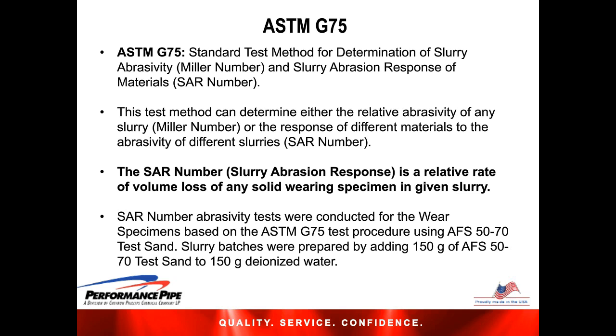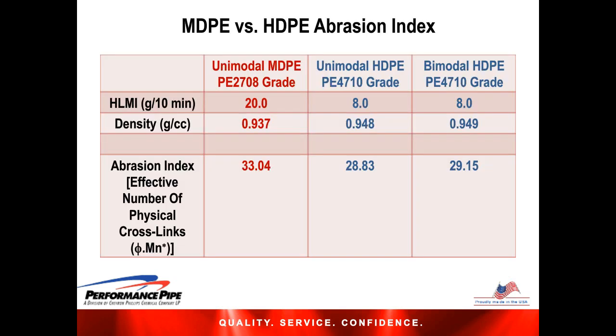We start by looking first at this table where we have listed the resin properties, primarily the high load melt index and the density. So again, the unimodal and the two high density resins. And shown in the lowest row there, what we refer to as the abrasion index, is using the same methodology and principles of the published paper that I talked about earlier. In going through the analysis, it showed that the medium density resin would have a higher abrasion index, meaning a better resistance to abrasion than either of the two high density resins. So this gave us a little more confidence in terms of the approach we were taking.